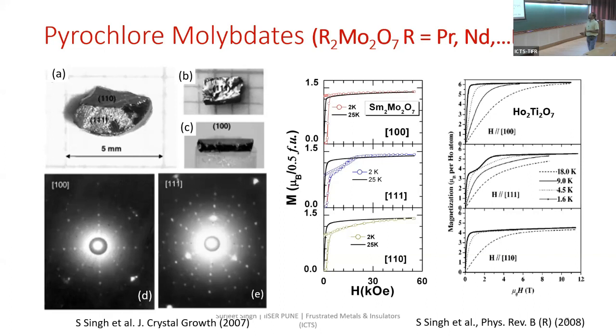by doing some bulk measurements, we showed that in samarium molybdate, the samarium ions undergo a spin ice kind of freezing at low temperatures in the background of the ferromagnetically ordered molybdenum spins. And this we inferred from the specific heat, but here I'm showing you the bulk magnetization data. And you can see, this is the experimental data on a classical spin ice compound, holmium titanate.